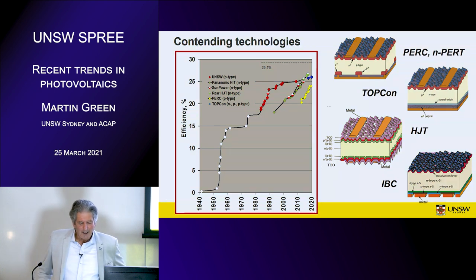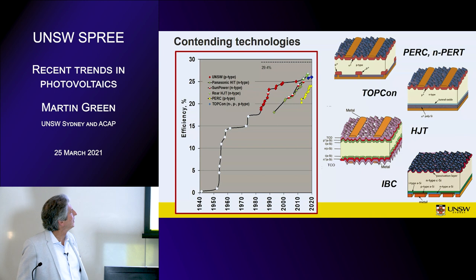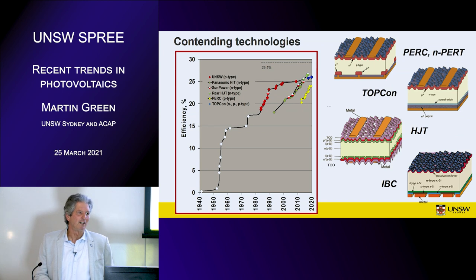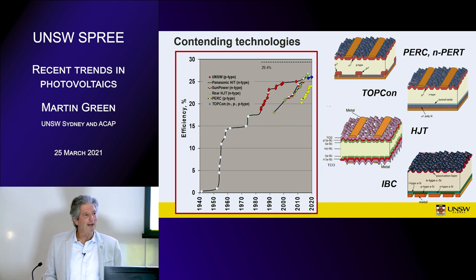Anyhow, going back to the spiel, all of these have a similar length of history, but if you look at the commercialization attempts, actually the heterojunction and the IBC have had a lot more serious work put into them than the PERC, in that there's about a 10-year gap between the two. So my theory has always been the PERC will catch up, because in the laboratory, when we were on a level playing field, we could always beat IBC and heterojunction, so why not in industry? So I've been a bit reluctant to believe that PERC can't match the other technologies in efficiency. It's just this delay in the industrial take-up of the technology that has caused the difference, because both IBC and HJT have had 15, 20 years of commercialization.